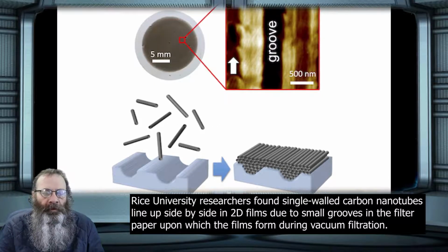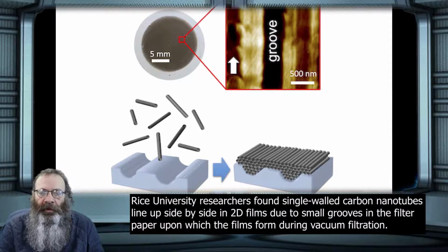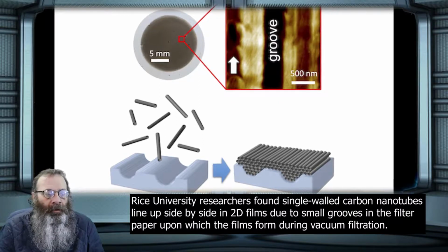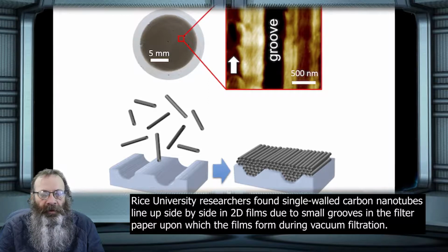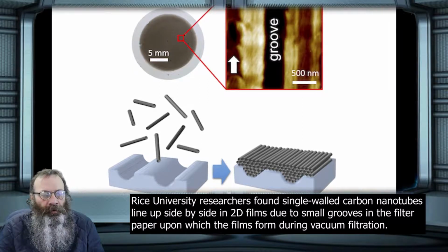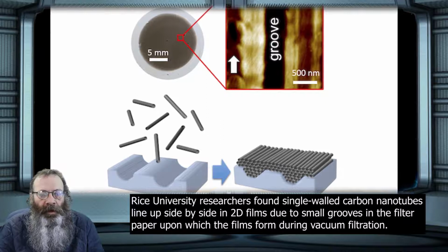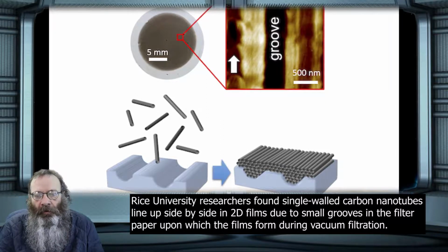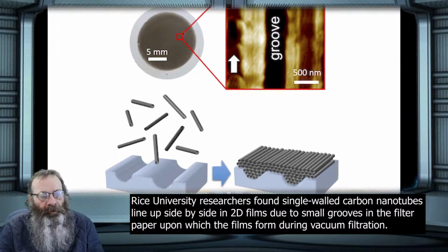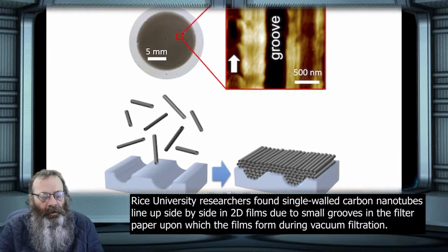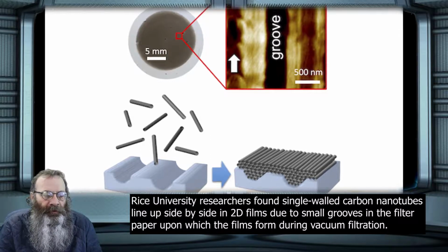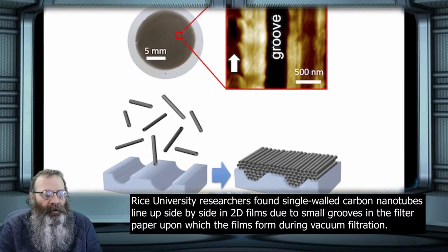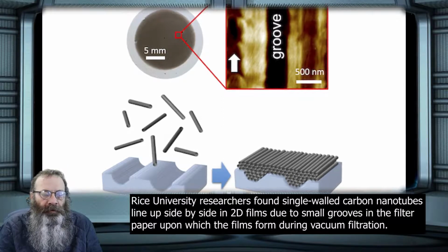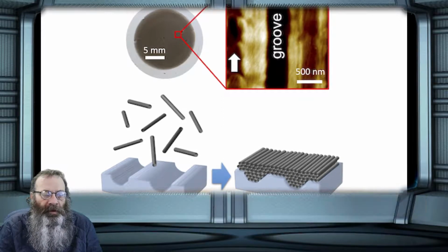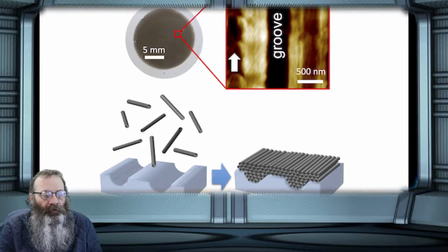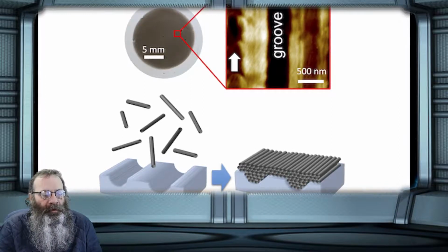The extraordinary optical and electronic properties of carbon nanotubes depend on their diameter and structure, or chirality. Some chiralities act like metals and others like semiconductors, and researchers have struggled for decades to find a way to make large, macroscopic objects like a wire or one of Kono's 1-inch diameter films purely of nanotubes with one diameter and chirality. That's obviously the next step. In this study, we still use a mixture of metallic and semiconducting carbon nanotubes with a diameter distribution. The next step is to apply this new method based on intentional groove making using a grating to achieve total control of alignment direction.